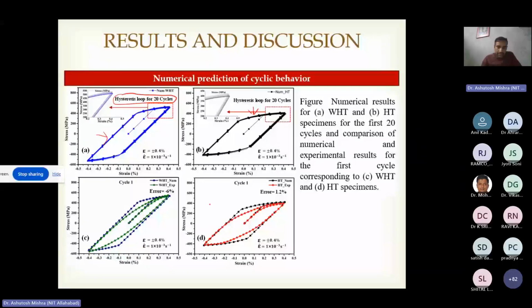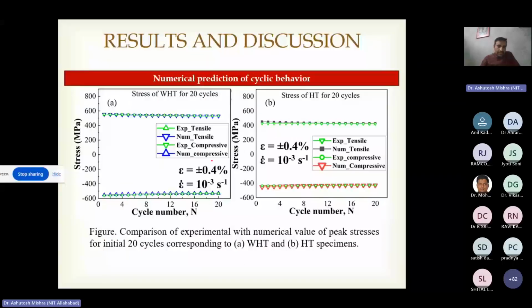Now, once the cyclic hardening is traced, I have carried out the test for stress versus cycle, that is, tracing the stress versus cycle number plot. If we see the numerical tensile, experimental compressive, numerical compressive, it means the compressive and tensile stress at each cycle, the positive and negative cycle, the maximum values are traced. The numerical and experimental curves are matching satisfactorily. For both WHT and HT specimens, I have carried out 20 cycles, and the parameters are identified. That has been published also.